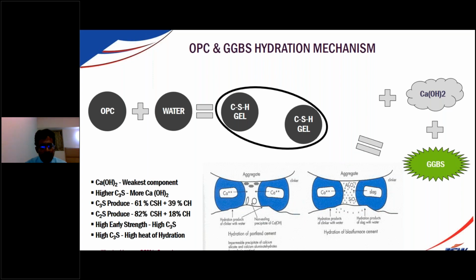We know nowadays high grades of OPC 53 cements are coming to the RMC plants. Everybody wants to copy it. How much strength am I giving after 28 days? That is the challenge everybody is giving to the market. All the cement companies say, my strength is more, my strength is more. But how is the strength more? Because C3S is more in the cement. If more C3S, as I told you, we are going to have lesser CSH gel and more calcium hydroxide. C2S gives 82% CSH gel and 18% calcium hydroxide.